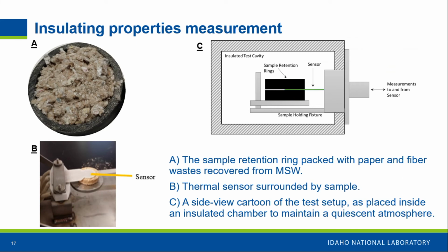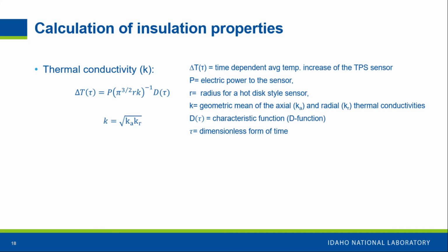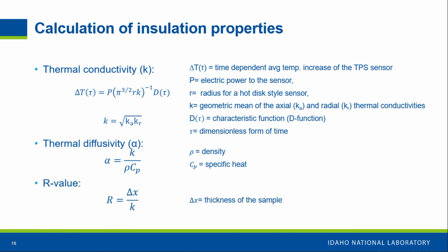So finally, we tested our material in terms of thermal properties. We used a transient plane source method where we packed our material with a certain packing density. We put the sample on a heat source, and we pass the current through a known resistor, and we measure the temperature difference of the material. When we record the temperature difference, we feed it into the equation to get the thermal conductivity. As soon as we know the thermal conductivity, we calculated the diffusivity as well as the R value, which is a commercially well-known number for cellulose as an insulating material.